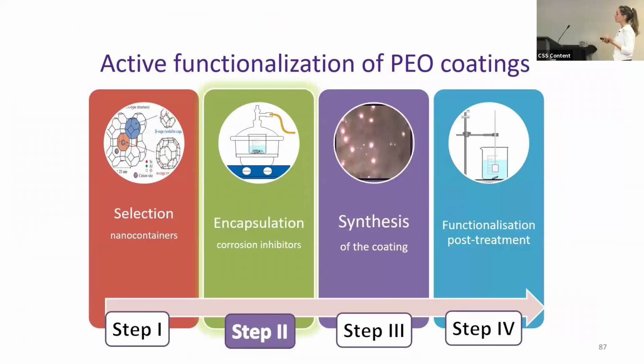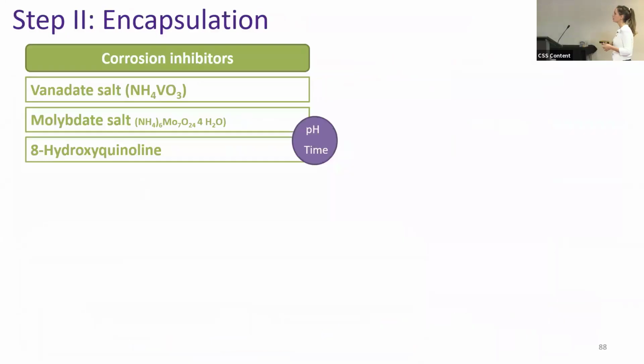So the second step is the physical encapsulation of the inhibitors into the nanocontainer. We have selected 3 different corrosion inhibitors. 2 of them are inorganic salts, vanadate and molybdate salts, and 1 organic. These inorganic salts are negatively charged, so the release trigger will be a pH change.